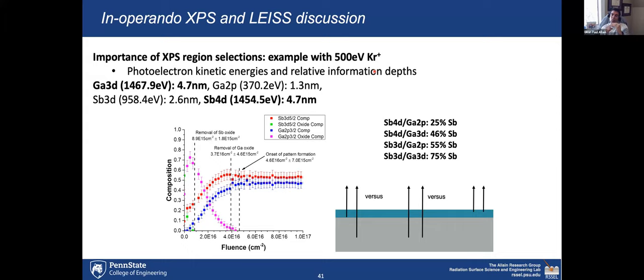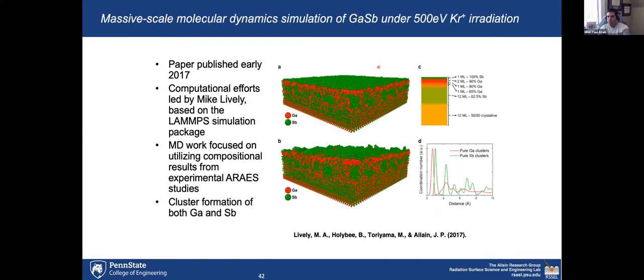And we found that it is in fact when the antimony actually reaches the first layer of atoms that we start getting the spontaneous patterning. We're continuing this study now, and there's a lot of work still in trying to understand this spontaneous patterning. And we're finding that there's an irradiation accelerated kinetics that is happening with the antimony and with the gallium atoms. So we're doing multi-scale atomistic simulations to understand this, to capture the prompt time scales that are missing in the experiment. And Mike Lively is working on this in his PhD work.